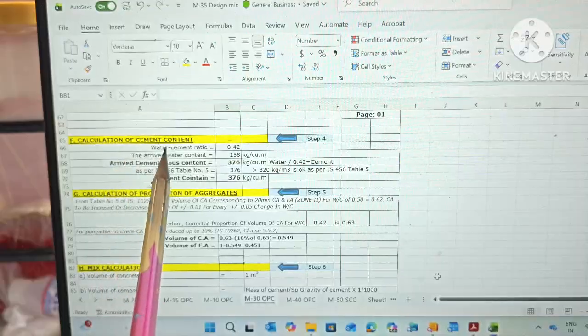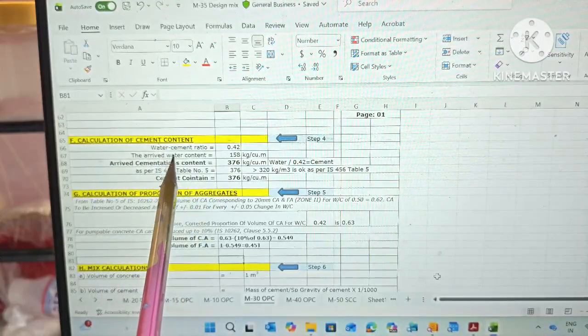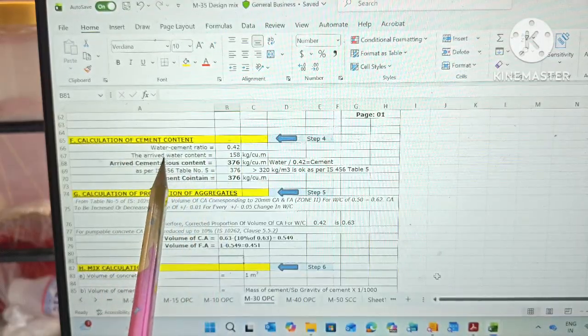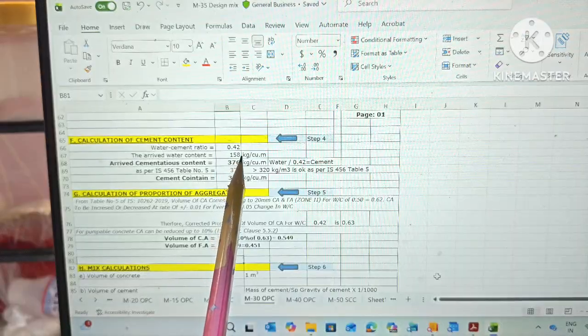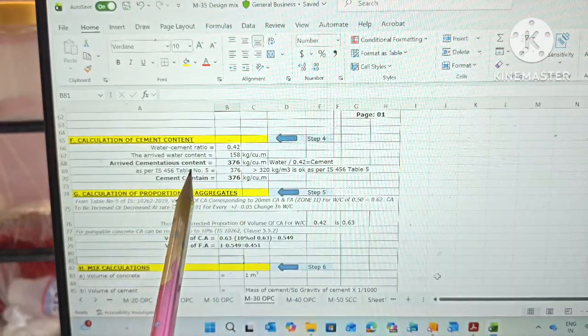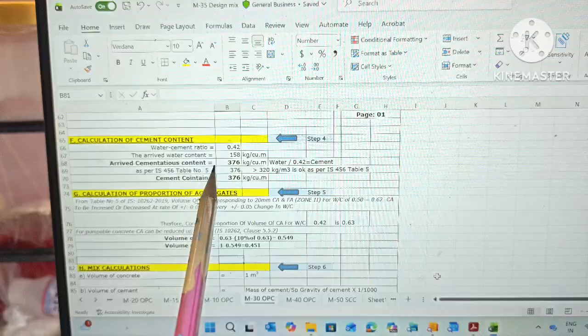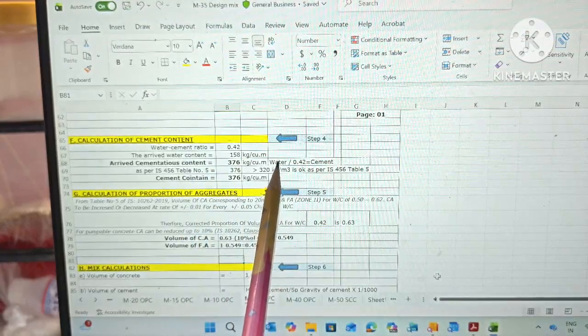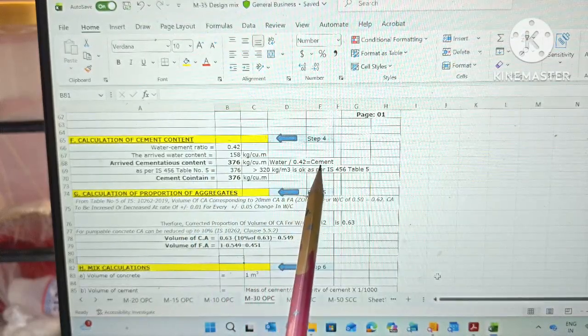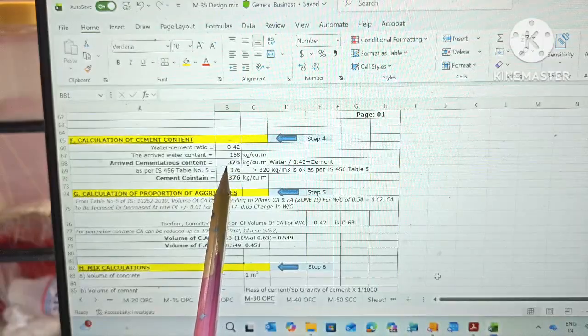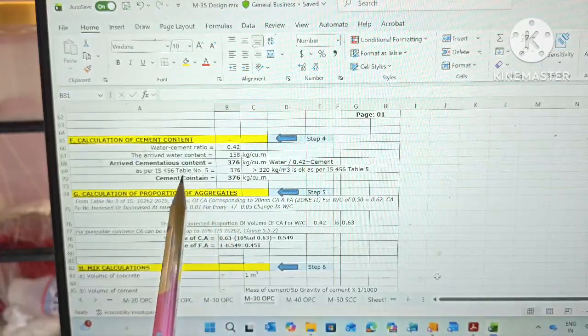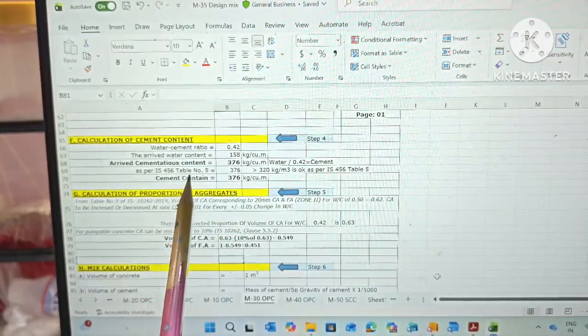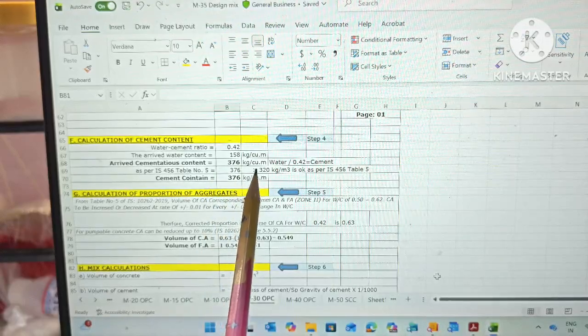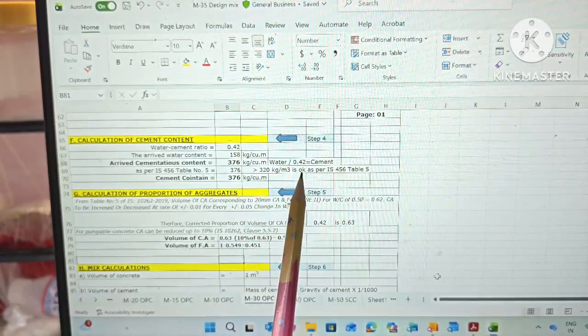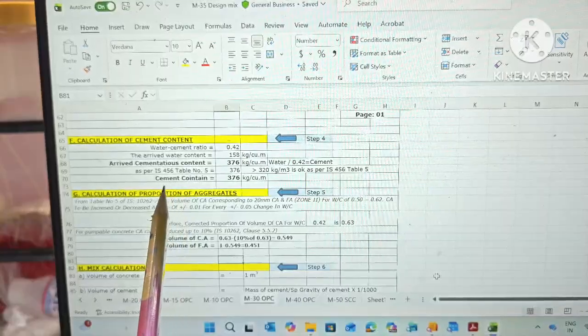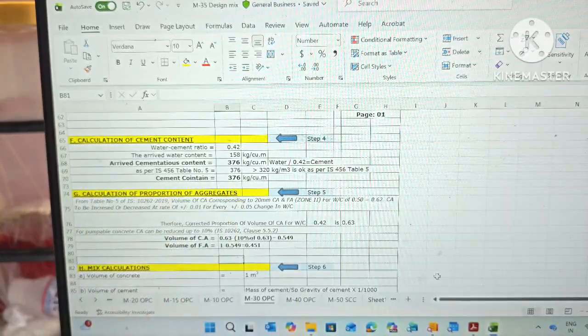Now step number 4 is calculation of cement content. Friends, we already have the water cement ratio of 0.42 and the water content of 158 kg per meter cube. We have to find the cement, so we know the water cement ratio is 0.42. So water divided by water cement ratio is equal to cement. So finally we get the value of cement as 376 kg per meter cube. Now as per IS 456 Table number 5, 376 is greater than 320 kg per meter cube. That means it is okay, it is accepted. So our final cement content is 376.